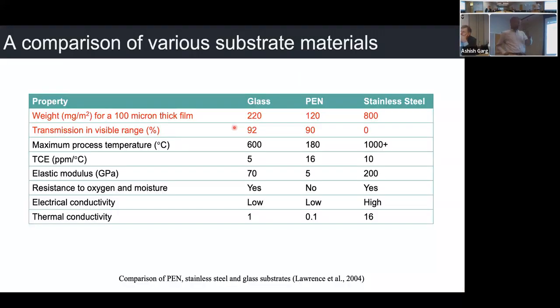So if you compare a variety of materials, first we have to look at the comparative parameters of steel and glass as well as plastic substrate. So I put in three substrates here. One is a typical glass substrate, another is PEN, which is a polymeric flexible substrate, and third is stainless steel. Now, if you look at comparative parameters, what is nice about steel is that the processing temperature is very high. It doesn't degrade at high temperatures. It doesn't soften if your processing temperatures are high. Whereas glass and PEN, depending upon processing parameters, have a tendency to soften, especially PEN.